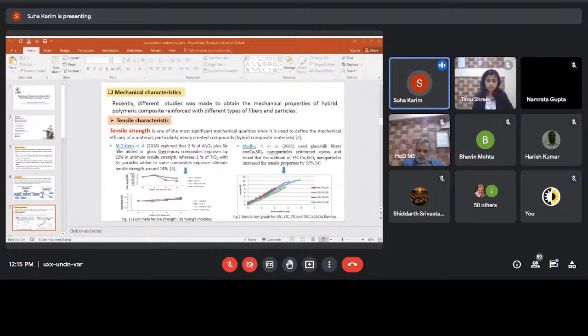Another research, Madhui in 2021, used glass with calcium silicate nanoparticles in an epoxy matrix, and they found that the addition of 3% of calcium silicate nanoparticles increased the tensile properties by 55%. One of the results of this research is shown in figure two, the effect of the weight percentage of calcium silicate on the tensile strength.